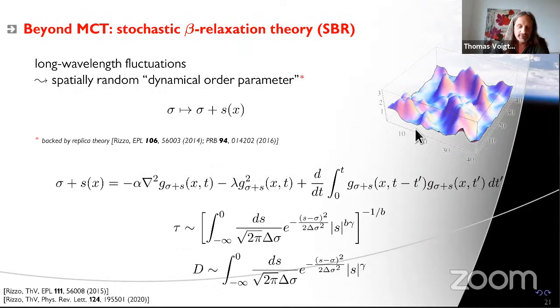And then arguments from replica theory suggest that what you need to do is extend Goetze's beta scaling equation by a spatially fluctuating component. So then everything becomes a function of x, which is just real space. And here as well. And if everything becomes a function of x, then in terms of this perturbation, you would also expect a gradient, or actually gradient squared for symmetry reasons. So there might also be this term. We figured out it's not very important in understanding what's going on. But the important thing is that you have a collection of, so to speak, patches in your system. Some of them relax slowly, some of them might not relax at all. And this is then the equation you should analyze. And then something interesting happens.